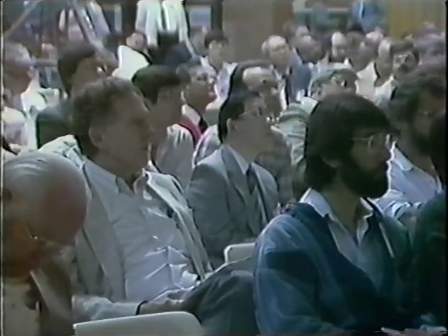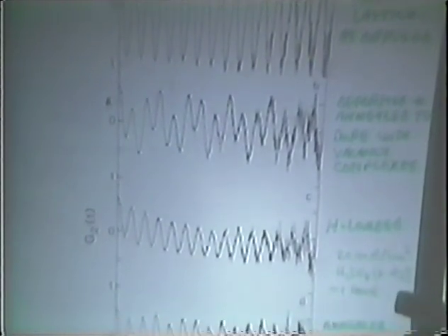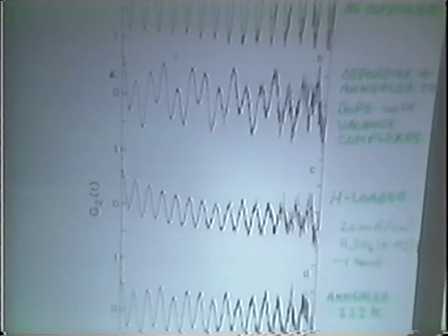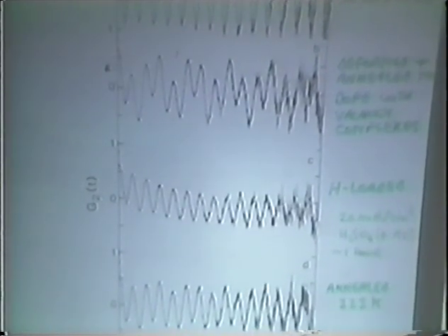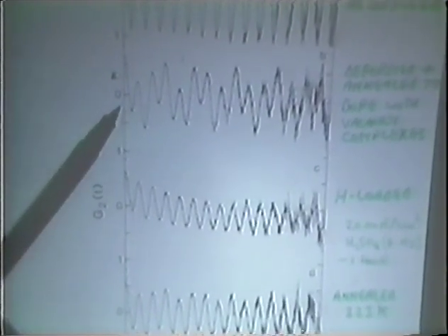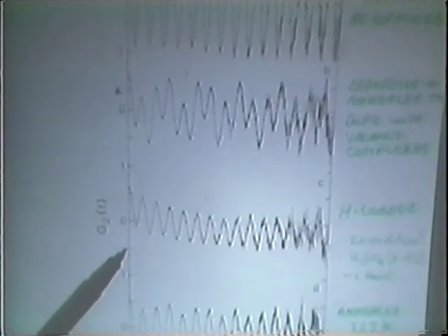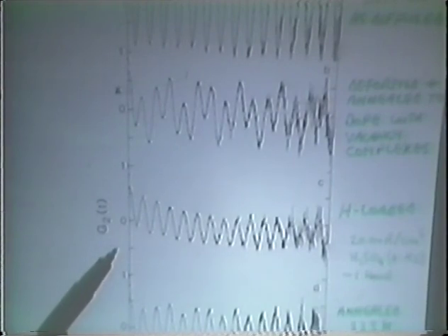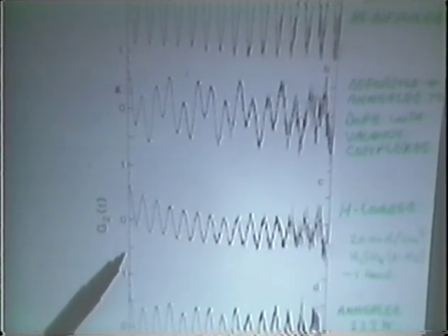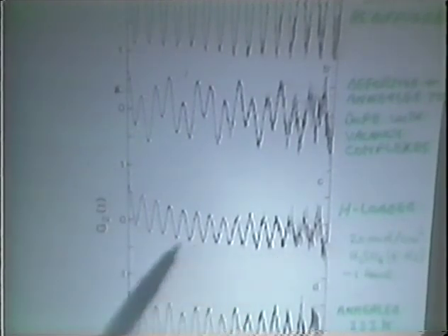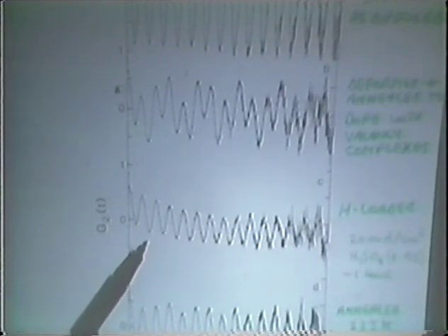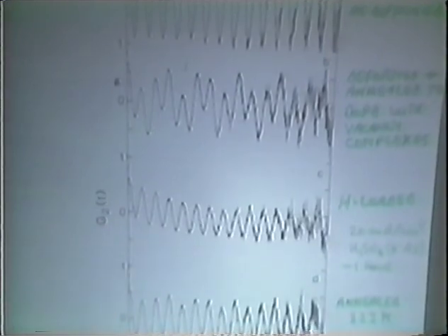Okay, now let's go on to hydrogenation. If we use this piece of nickel now as an electrode, a cathode in a little electrolytic cell, we can observe the following kinds of changes in the signal. This nickel sample was loaded with a 20 milliamp per square centimeter current for about an hour in a 1 molar H2SO4 solution with a little arsenic, a recombination poison, and as you can see, there's an apparent complete disappearance of the low frequency signal. The reason is that we've trapped at least one hydrogen atom in each one of those cubic complexes, and we've destroyed the cubic symmetry. The result is that you see only the high frequency signal for the substitutional indium atoms, which remains there because the hydrogen atoms do not trap next to the substitutional indium atom.